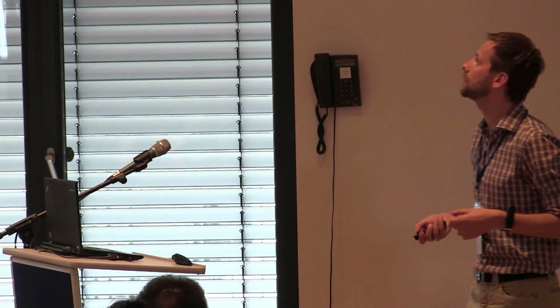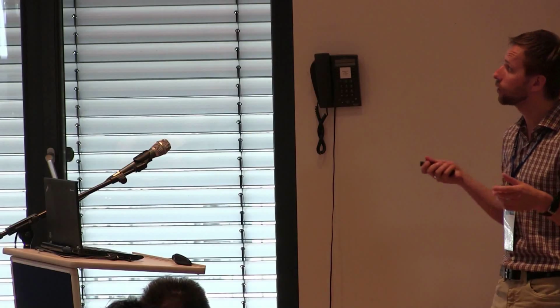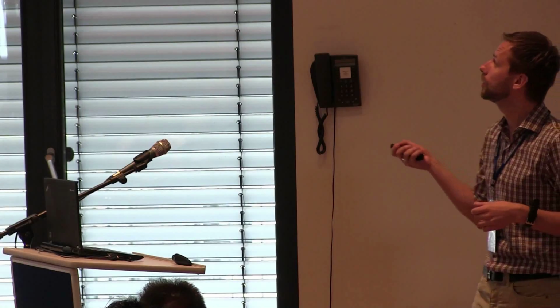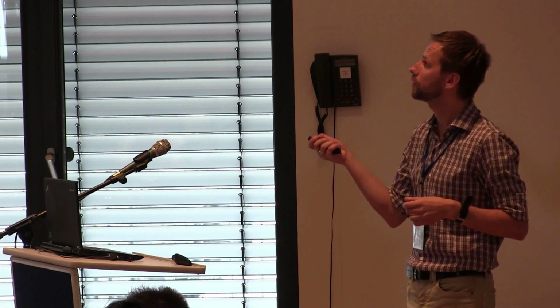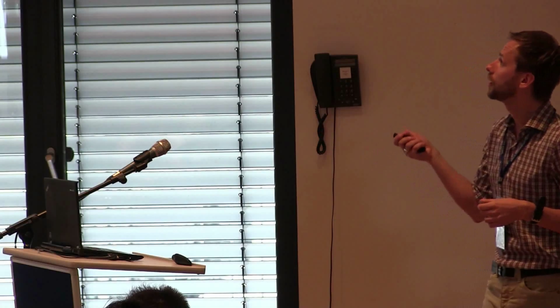So we decided to be very general and to build the model from first principles by considering the dynamics of electron heat in graphene. So we know that you deposit the heat instantaneously. So the electrons in graphene thermalize instantaneously when they receive new energy. But they cool down slowly because cooling of electrons in graphene occurs via phonon emission, and the dynamics is known. So the heating is instantaneous, a few femtoseconds, cooling down slow, picoseconds.